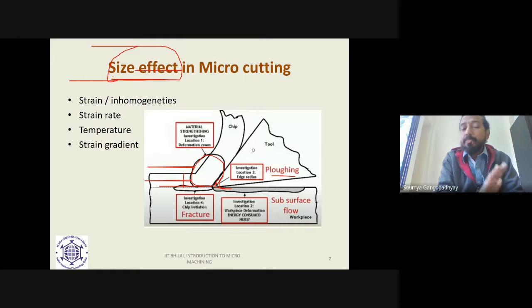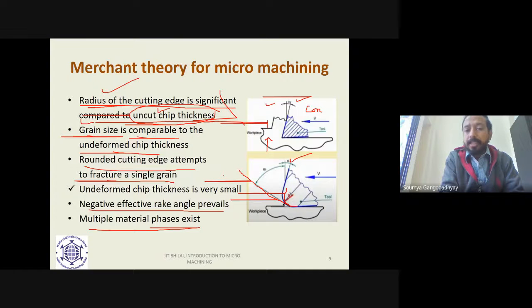This is the most fundamental aspect in micromachining, which is characterized by size effect. In macromachining, there is no size effect because the undeformed chip thickness is high, because the feed is high. But in the micro cutting regime, the size effect dominates, and therefore it makes it challenging, and it actually leads to the high specific cutting energy.